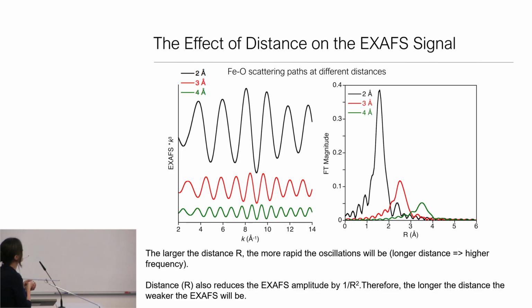And what you can very nicely see is how the frequency changes. The longer the distance, the higher the frequency. So the frequency of the beat in your XAFS immediately tells you something about how far away the scatterers are. But if you don't visualize well in frequency space, you can also see it in R space, where we go from 2 to 3 to 4 angstroms, and you nicely see this 1 over R squared dependence. That's what makes XAFS a local technique, right? So the longer the distance, the weaker the XAFS will be.